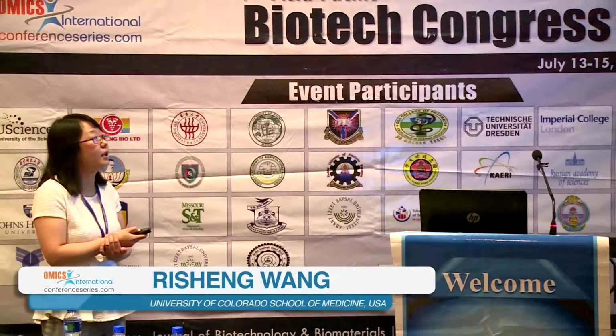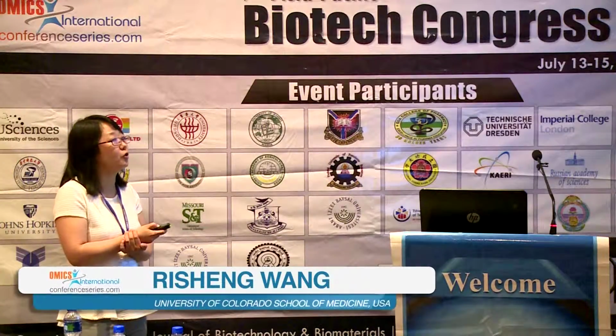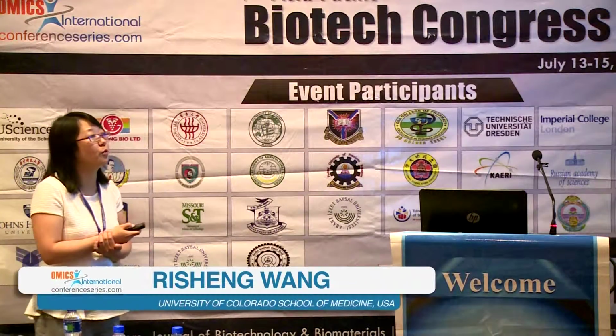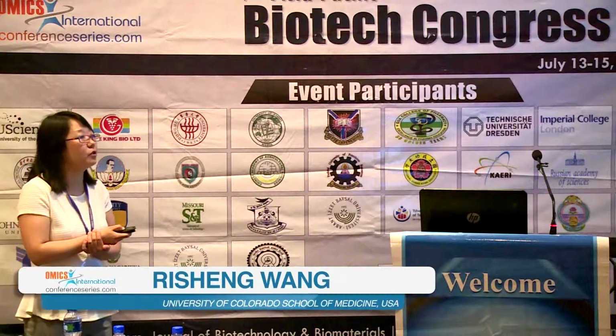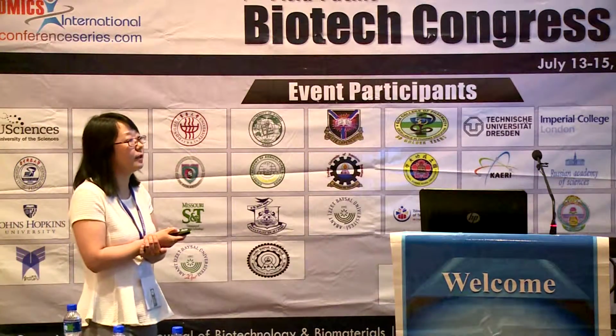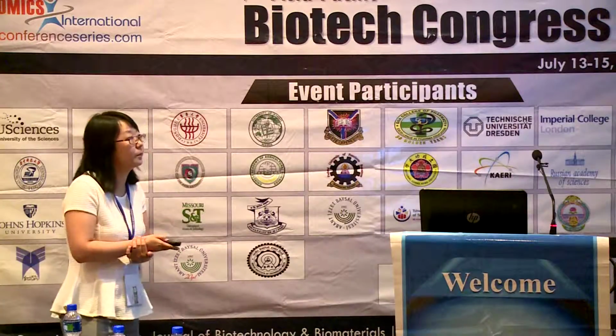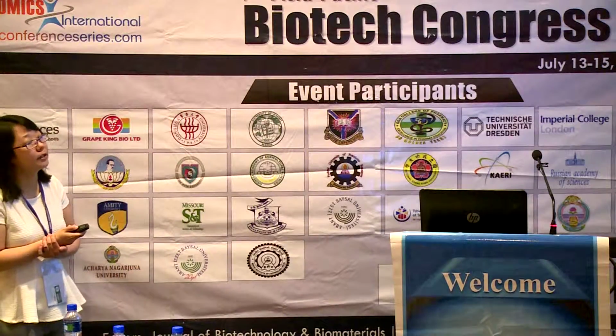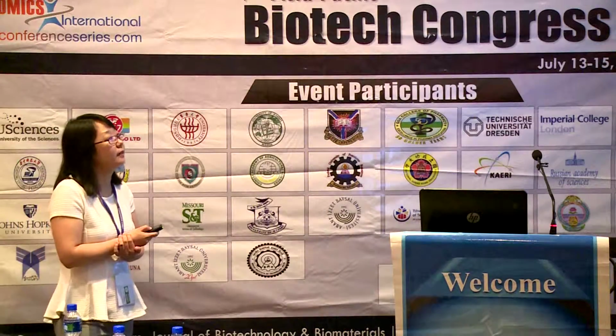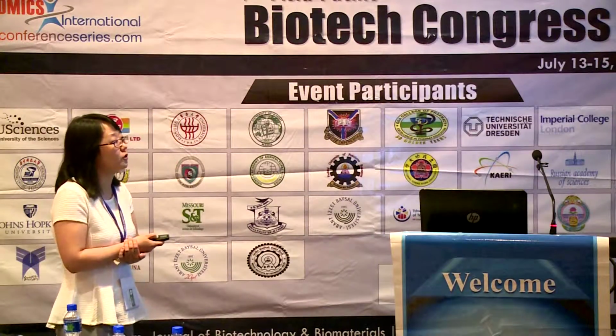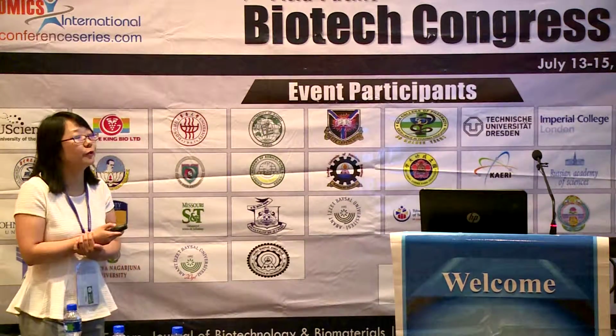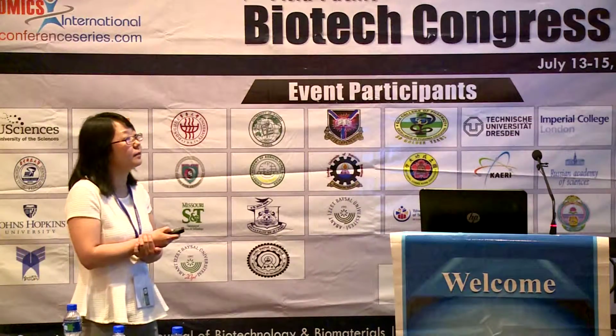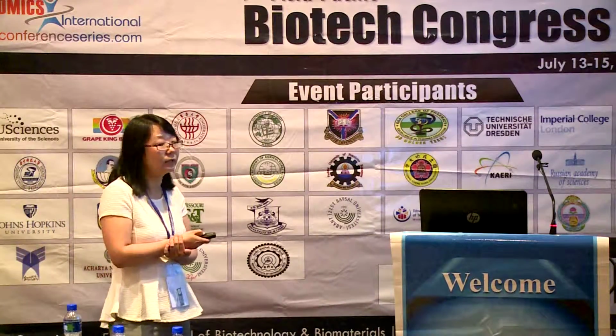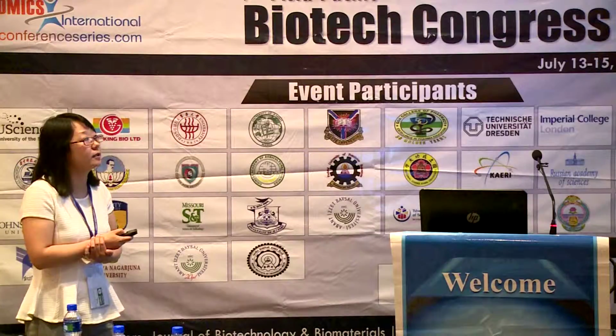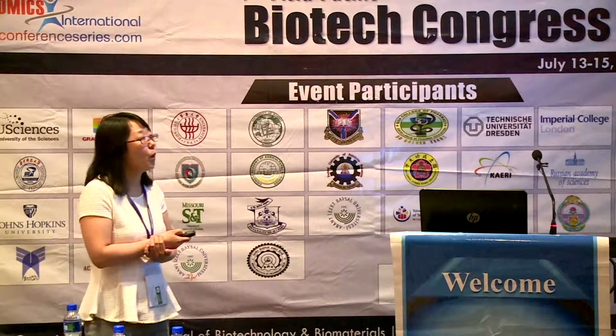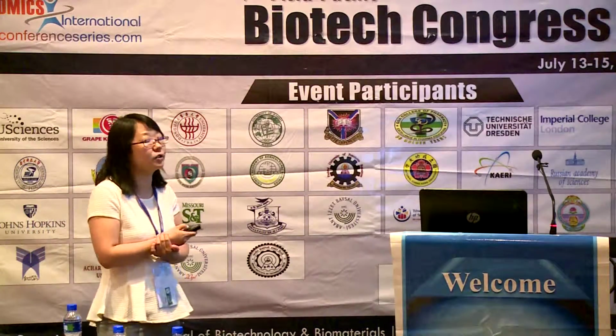So this is the DNA nanostructure. It's two DNA double helices joined together by five crossover points. This is how we imaged it on the mica surface. We can see it forms a rigid DNA nanostructure. Here's the experiment result. This is the one-dimensional DNA nanostructures attached on the dot pairs. We get the fluorescence image. Each light spot corresponds to one dot pair. So it means for each dot pair we have at least one one-dimensional structure attached to it.